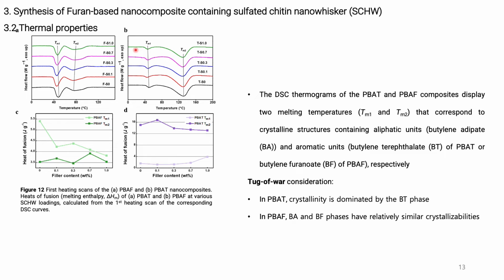The aromatic melting enthalpy ΔHm2 of PBAT is significantly higher than the aliphatic melting enthalpy at all nanofiller loadings, which indicates that the crystallinity is dominated by the BT phase, as we can see in figure 12C here. In contrast, in the PBAF nanocomposites, the opposite trend was observed. The heat of fusion of the aromatic BF segment was slightly lower than that of the aliphatic segment here, which indicates that the BA and BF phases have relatively similar crystallizabilities.